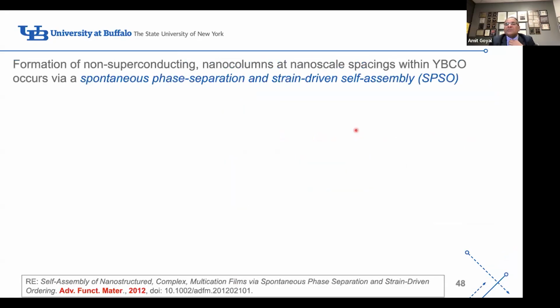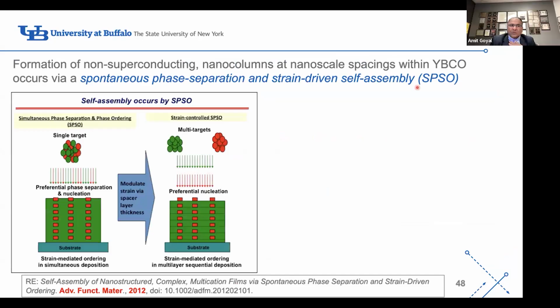So we understood this process. As I mentioned before, it is a spontaneous phase separation and strain-driven self-assembly process. So one way to study this: when we made the films originally, we had put nanoscale barium zirconate inside the superconductor on a single target. We made the film using pulsed laser deposition, and we got these nanocolumns.